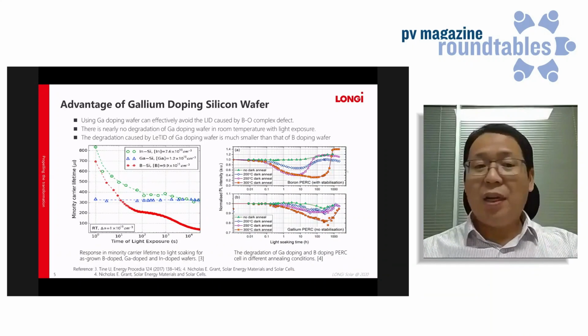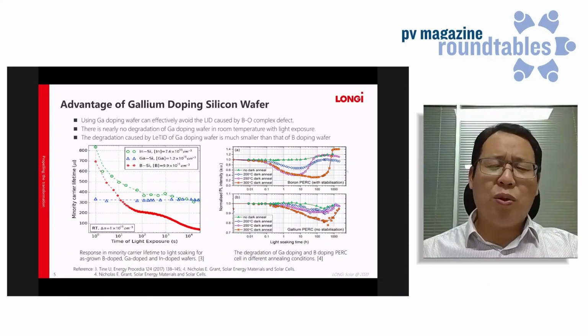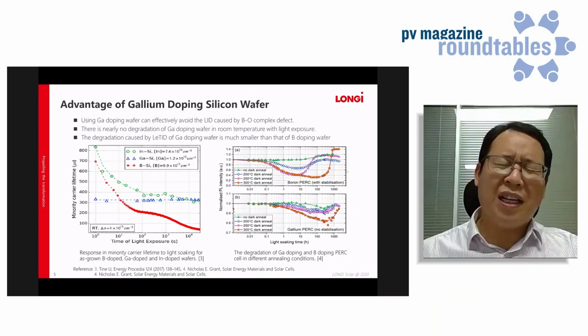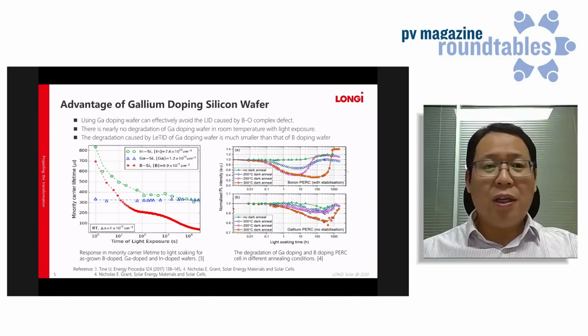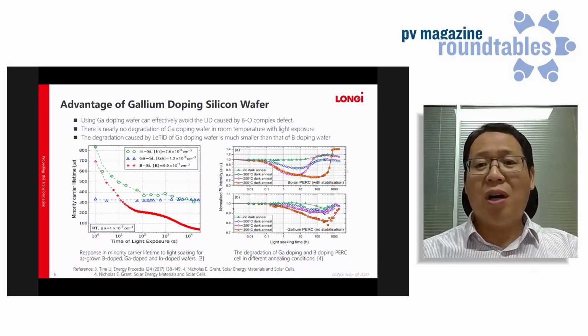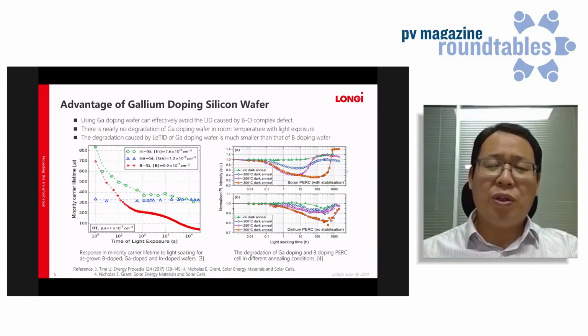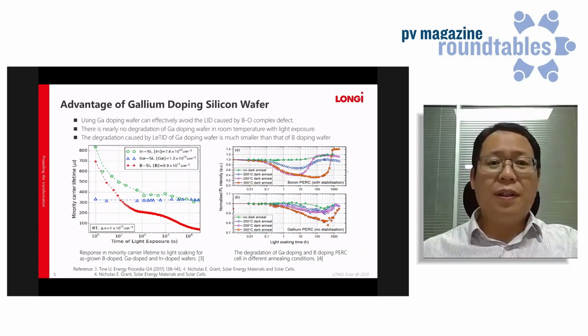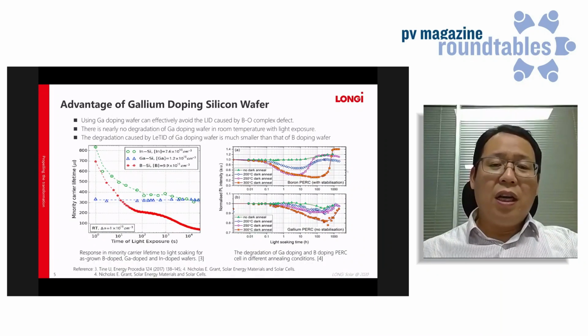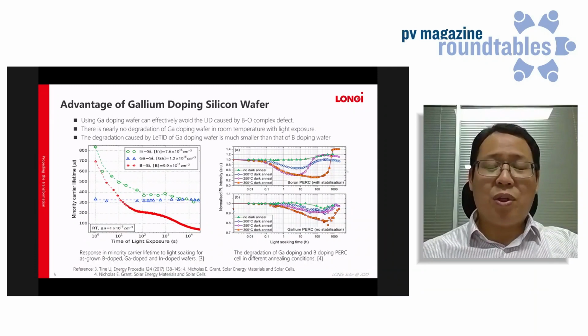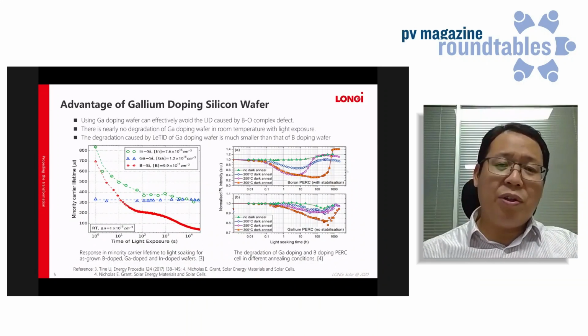As we know, gallium, like boron, is also a trivalent element. It can be used instead of boron in the P-type wafer as a dopant. So if we use gallium as a dopant, we can avoid the boron-oxygen complex defect. This will help us to reduce the degradation of the cell. As we studied, at room temperature, if we use a gallium doped wafer, there's nearly no degradation of the cell, which is shown in the picture on the left side. You can see that with a gallium doped wafer at room temperature after long time light exposure, the efficiency keeps very stable and almost no degradation.